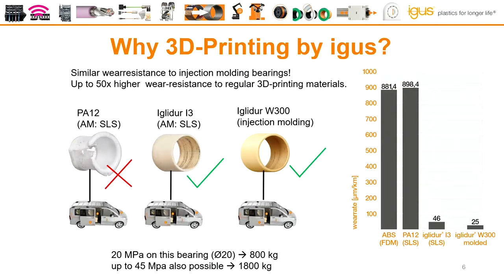And you see the printing materials like ABS or PA12, the regular printing materials, have a much higher wear rate, so they are wearing down much quicker. That's the big difference, not only for bearings, also for the gears here.